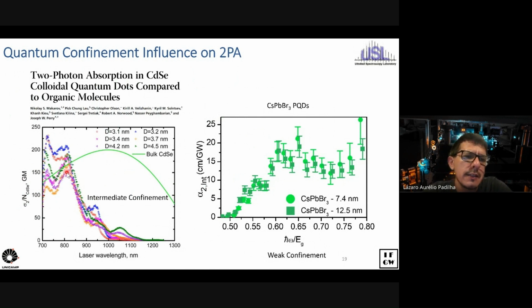One may argue that there is a factor of 2 here, but if you cut off the experimental errors, I would tell you that you are not really getting any big difference here if you compare to the bulk. They are really close. In these quantum dots, they are in the weak to intermediate quantum confinement regime, when the quantum dot size is nearly about the same as the exciton Bohr radius.